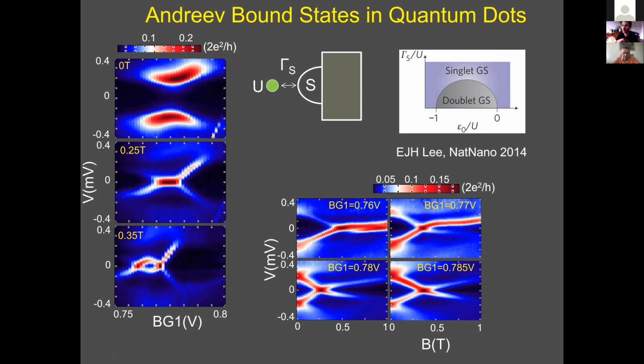What in general makes the picture slightly asymmetric with respect to the zero line? So it is largely symmetric, I would say, but yes, there are some asymmetries. There are several components to understand asymmetry. First of all, of course, in superconductivity, we have this emergent particle-hole symmetry. It is emergent, so in principle, it doesn't have to be exact. And especially when the Fermi level is not orders of magnitude larger than the single particle energy, it's possible, but we don't think that's what's happening here.